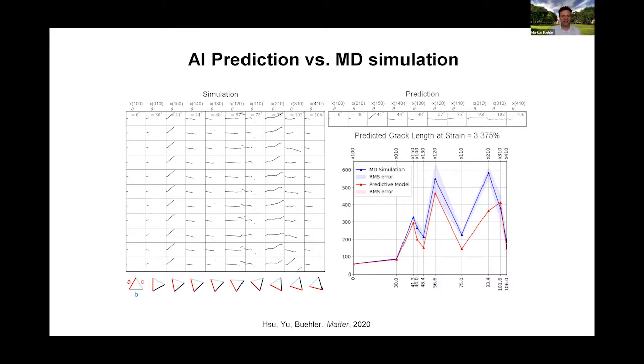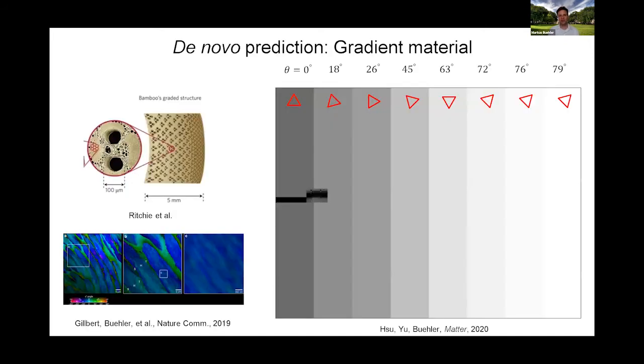You can see on the right-hand side is probably the most illustrative plot, comparing the MD simulation prediction with the AI prediction, and you can see that the orientation dependence of how the crack changes as you change the orientation is very well reproduced. We can use this model not only for situations we have trained it against, which is, of course, good that it works, but it's not enough. We want to be able to be predictive. We can also apply this to situations that we have not trained for.